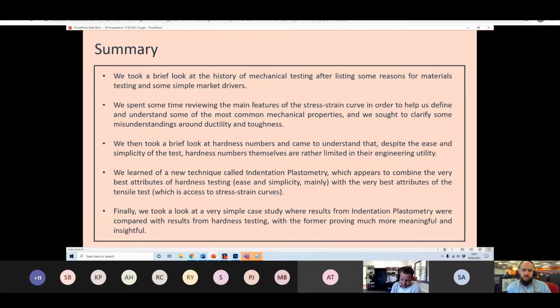I can. And we tried to do this, albeit in a very simplified sense, by showing what the algorithm is doing, because that's where the science is. Okay, the machine is just a test machine. But what's really useful or helpful for us is the software. What's going on is an inverse finite element analysis technique. And again, conceptually, that's very, very simple. We are just comparing a predicted profile shape with a measured one. And we're sort of saying to ourselves, well, what properties did the material have to have to obtain a profile shape like that when it was indented under those conditions?